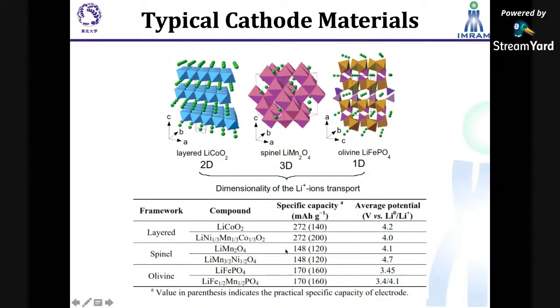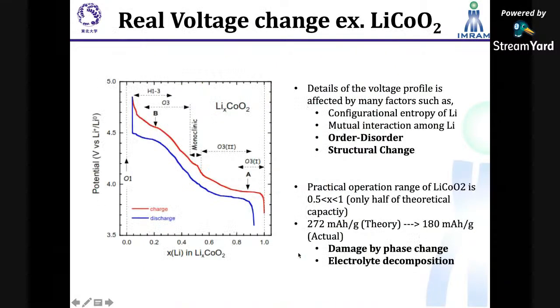And similarly, in the case of lithium manganese oxide, the theoretical specific capacity is 148, and only 81%, up to about 120 milliampere hour, has been extracted. And in the case of lithium iron phosphate, about 95%, 160 milliampere hour per gram, has been extracted. So what restricts the capacity? Why can we not extract the complete capacity from lithium cobalt oxide and lithium manganese oxide? So I will explain this.